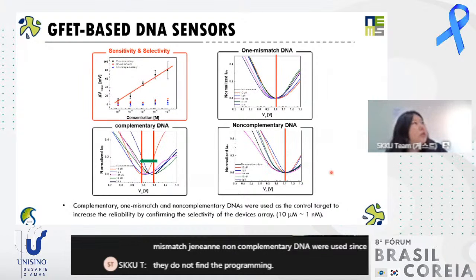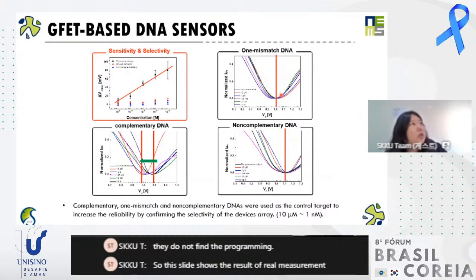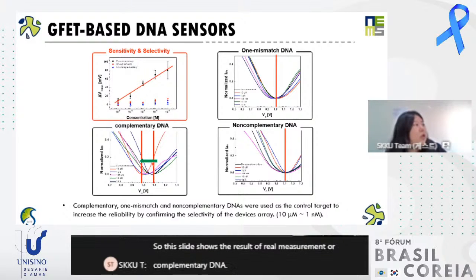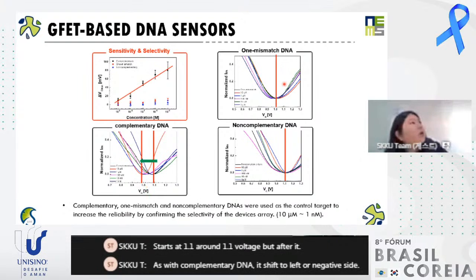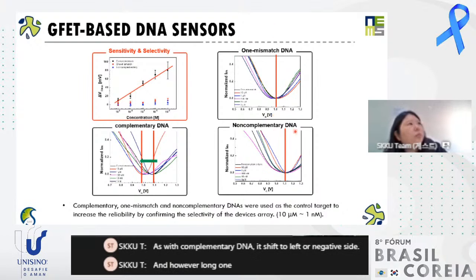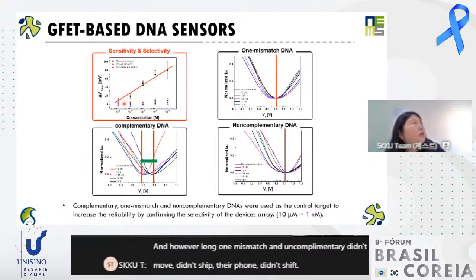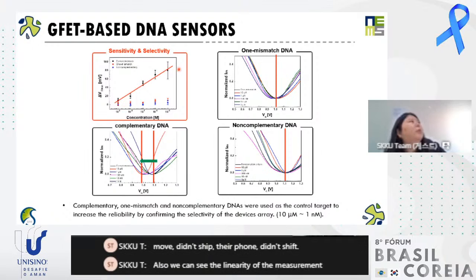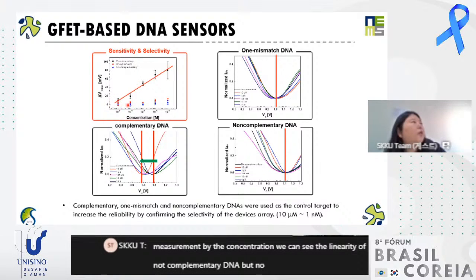So this slide shows the result of the real measurement. Complementary DNA starts at 1.1 volts, but after it hybridized with the probe DNA, it shifts to the left, negative side. However, the one-mismatch and non-complementary DNA didn't move. The Dirac point didn't shift. Also, we can see the linearity of the measurement by concentration for complementary DNA, but no such characteristic with one-mismatch and non-complementary DNA.